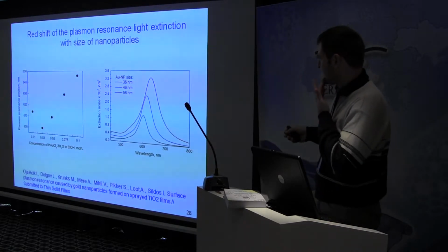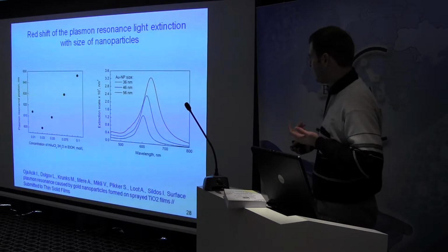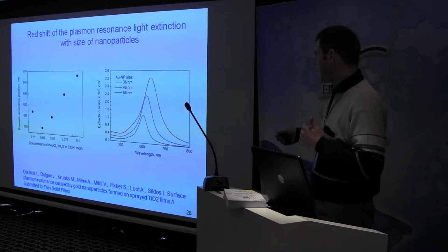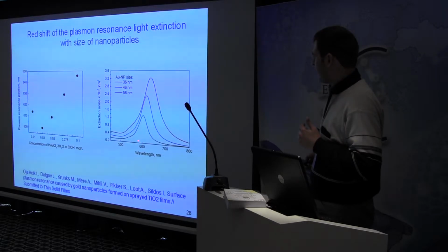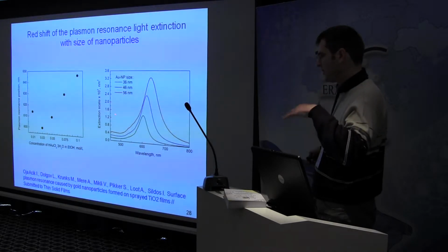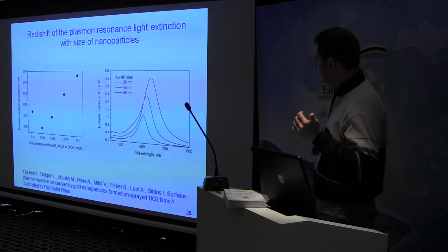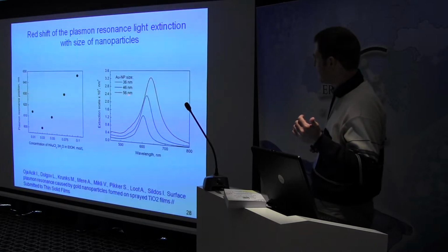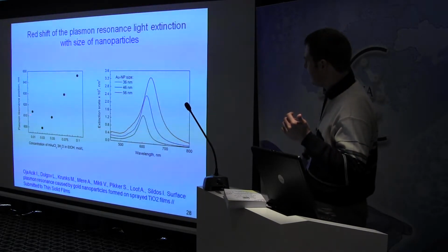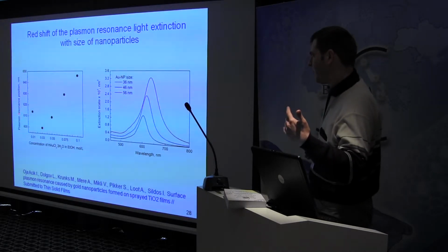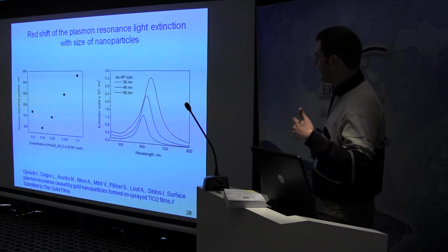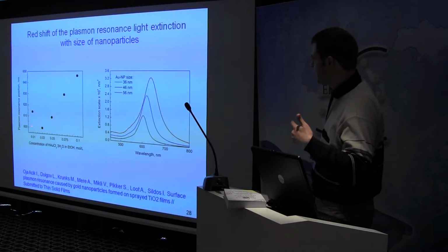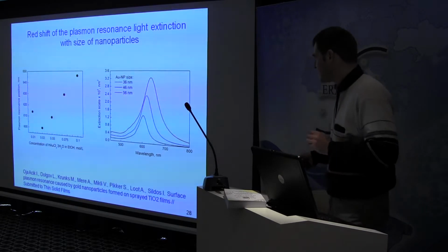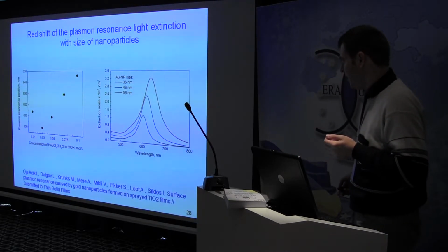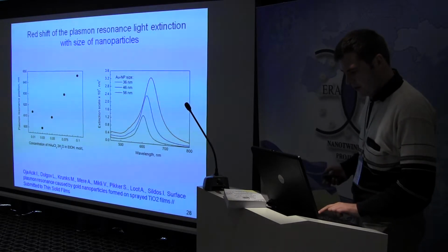gold nanoparticles. And if we model the situation, for example, on average for spherical particles, we obtain the same shift in light extinction for gold situated inside titanium dioxide, a little bit of a red shift with the increase of the size of the particles. And the same in the experiment: when we increase the concentration of gold salt, we obtain bigger particles, and we also have some red shift in the resonance. So we also submitted these results to the Thin Solid Films journal.